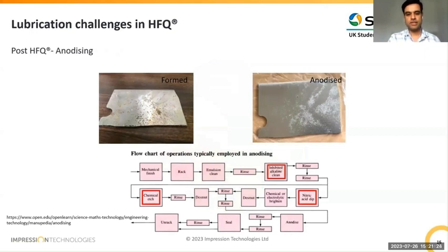And this is one such example of that. This is a section of a formed part, which has some remnants of the lubricant that was charred and did not get cleaned properly. And then we sent it for anodizing. And anodizing is a very rigorous process in terms of the cleaning and etching. And despite that, the lubricant was not removed. And essentially, this part was considered a defective one.